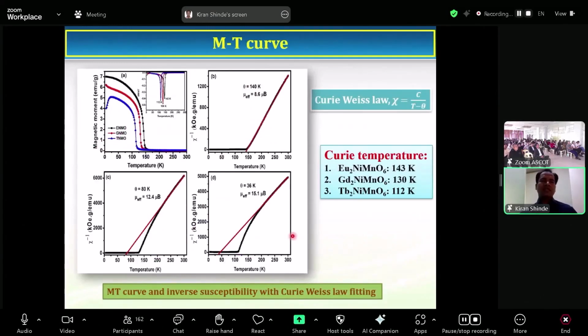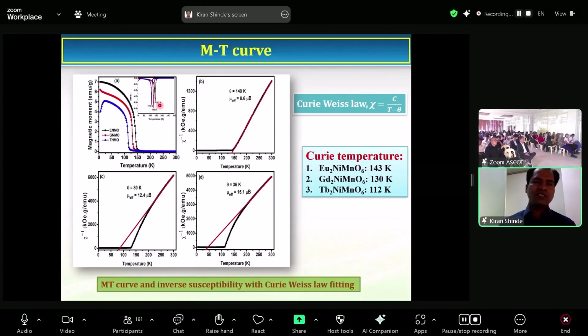In this slide, we can see the magnetic moment with respect to temperature, the MT curve, which we use for the determination of the Curie temperature. So here we can see that for europium, gadolinium, and terbium based compounds, we measure the magnetic moment and we take the differentiation of this magnetic moment with respect to temperature. Then here we can see in that plot, we get the minimum in this dM/dT curve, which is nothing but the Curie temperature. So when we change the europium, gadolinium, and terbium, three different rare earth elements at the A site of the double perovskite, then we found that the Curie temperature is changing from 143 Kelvin to 112 Kelvin.